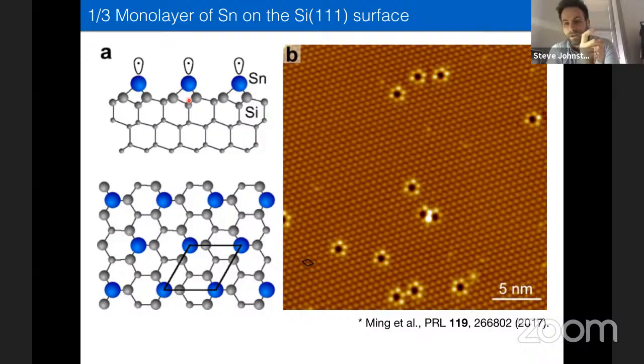The orbitals are pointed perpendicular to the surface, and they're separated by quite a large distance. And so the orbital overlap between these dangling bonds is actually quite small. So they're a very narrow bandwidth system. And it turns out that that bandwidth actually becomes comparable to the Mott-Hubbard interaction that you would calculate for that dangling bond. That's really what we think drives the Mott physics.